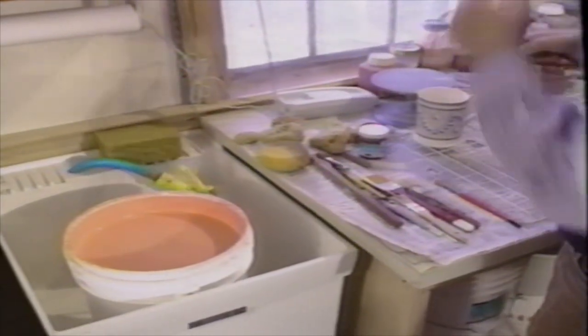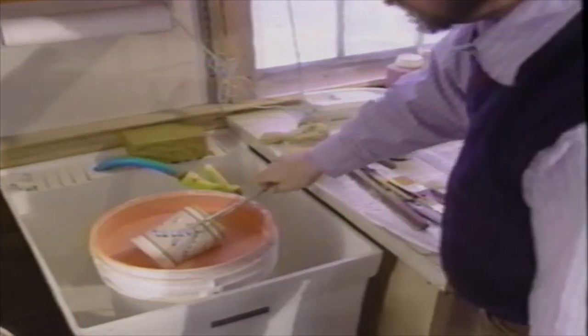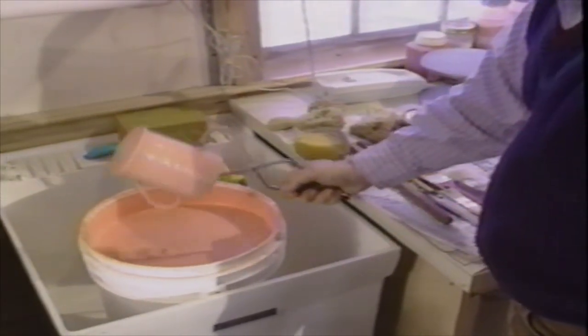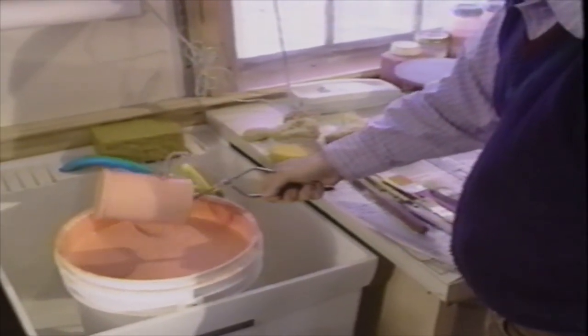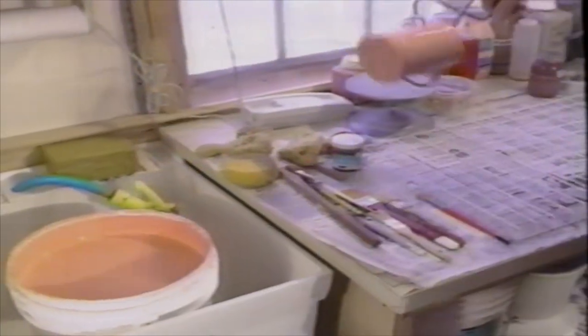The plate Don is making could be either creamware or pearlware, depending on the glaze. Before glazing, objects are biscuit fired at a higher temperature to solidify the body. The clear lead glaze for creamware typically was contaminated with iron and manganese oxides, giving the ware its typically yellow cast, whereas pearl glaze included small amounts of cobalt to act as a whitener.